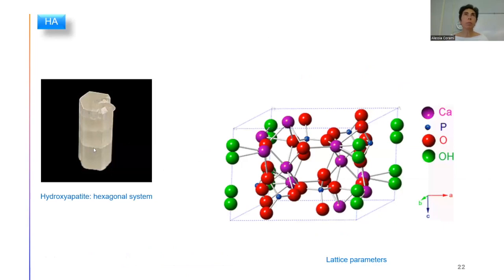Mainly phosphates are stable to different environmental conditions. They show a low solubility. Hydroxyapatite crystallizes in the hexagonal system, and this is an example of the 3D cell. And it's important to understand that generally the heavy metals that can be sorbed by phosphate can substitute calcium. Calcium has two positions, calcium 1 and calcium 2, and generally the metals could substitute calcium in position 2.